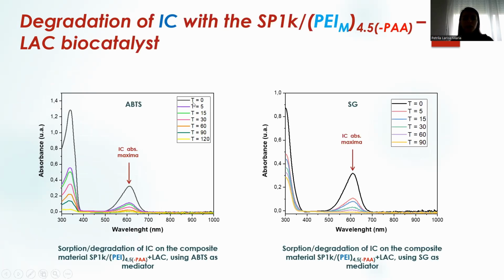We also assessed the use of the biocatalyst obtained by the immobilization of laccase in the degradation of indigo carmine, both in the presence of ABTS and syringaldehyde. For the first biocatalyst obtained by the immobilization of laccase on the composite material fabricated with polyacrylic acid, we obtained a 96% discoloration efficiency after 1 hour, while when using syringaldehyde as mediator, the discoloration efficiency was 100% after 1 hour, results that confirm that the immobilized enzyme is still active and still able to lead to indigo carmine degradation.